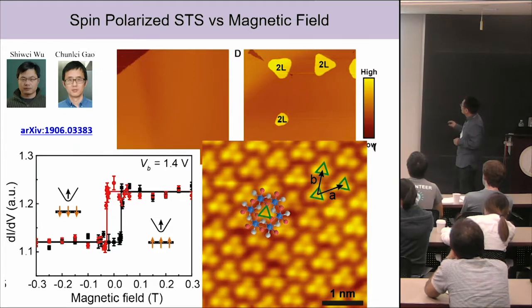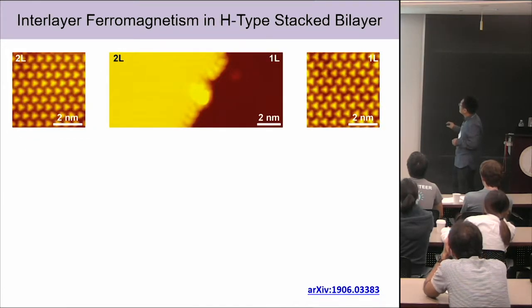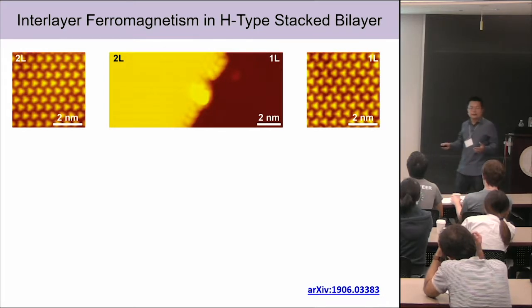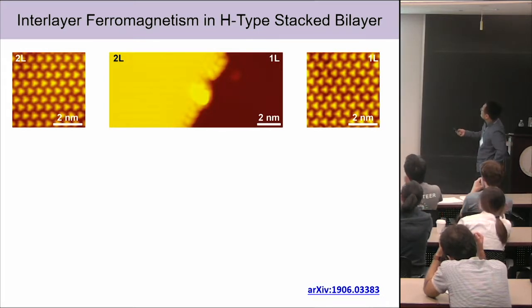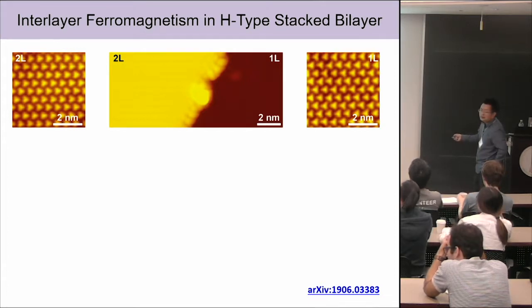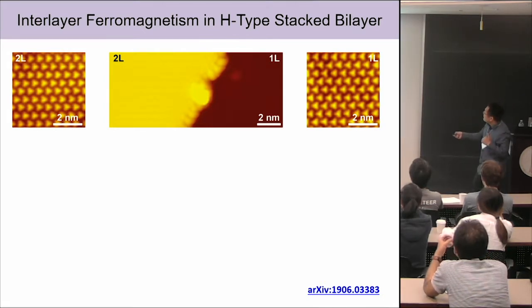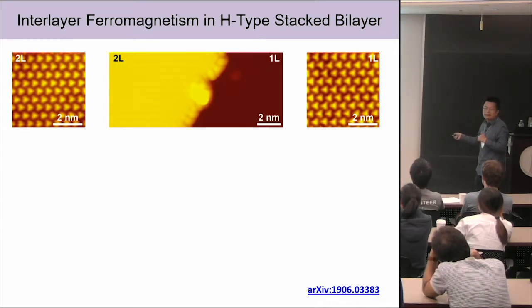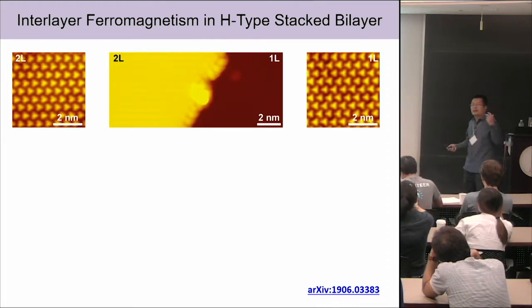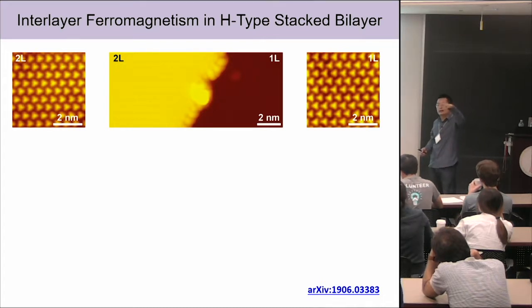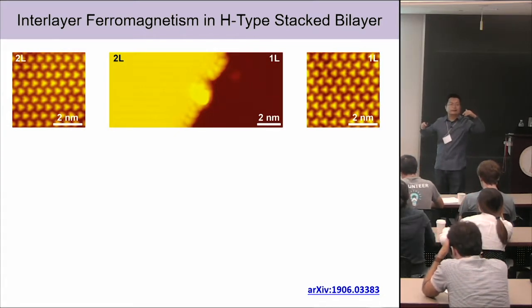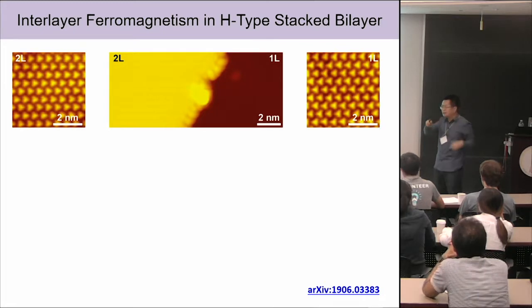Well, then we can also look at the bilayers. Now this is the interesting result. In the bilayer, you can image the atomic structure of the top of the bilayer. Then you know the orientation of this triangle, right? By imaging the top, you know the triangle orientations. Now you can also image the bottom layer, which is the extended monolayer underneath this bilayer, right? We extend out. So then you can map out the triangles of this bottom layer. So basically now you know the triangle orientation in the top layer, and you also know the triangle orientation in the bottom layer. Make sense, right? Then you can put them together.